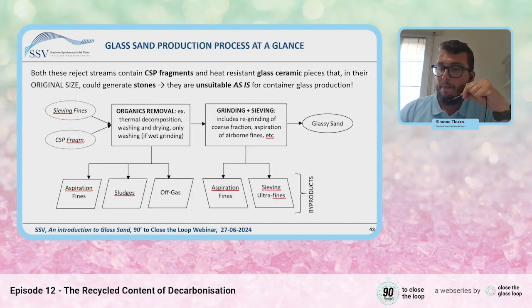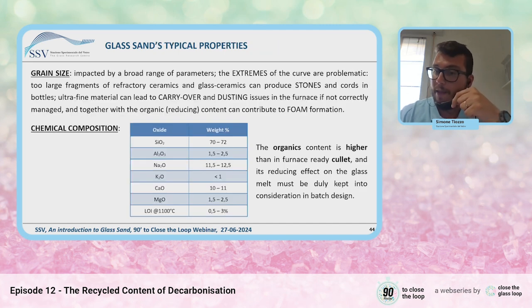And how do we do it? Basically, the companies that make glass sand mix the sieving fines and the ceramic rejects in different and appropriate proportions. They apply several protocols for the pretreatment of this material, for example, to remove the organic contaminants, or other pre-selection to remove some CSP fragments and so on. Then they grind this material to a suitable grain size, typically below 0.8 millimeters. They also sieve it above a certain threshold to take out the ultrafines that could lead to several other issues in the furnaces. And then this material is provided to the glass makers that can recycle it in their furnaces, in addition to normal furnace-ready cullet, and they can use it to produce new bottles.